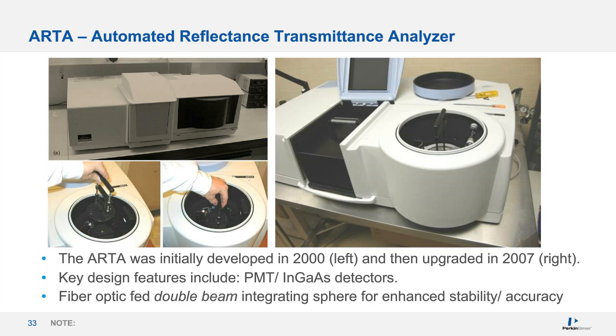Indeed, essentially any sample detector configuration can be prepared in an automated fashion to generate reflectance as well as transmission data. The key features of this accessory were the incorporation of an integrating sphere type detector assembly, which is critical for these types of measurements. Furthermore, contained within the sphere were the powerful combination of a PMT and an InGaAs detector for the near-infrared to offer unprecedented performance across the entire wavelength range. Lastly, a fiber optic bundle was used to feed the reference beam into the sphere, making this a true double beam integrating sphere detector.